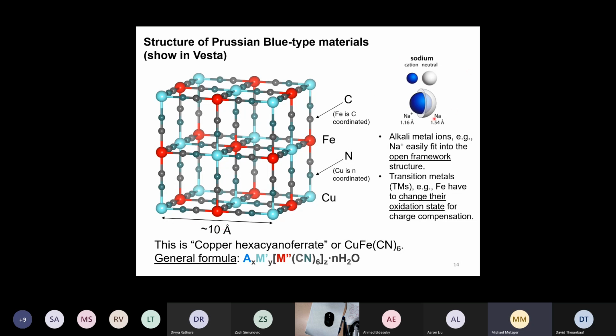And here on the right side, I drew the ionic radius of sodium, because, from the name Natron Energy, you can already infer that they use sodium as the intercalant alkali metal. So you can see this is fairly small compared to these large interstitial sites that you have in this material. The cool thing about these open framework batteries that use these Prussian blue analogs is they can readily intercalate different types of alkali metal ions.